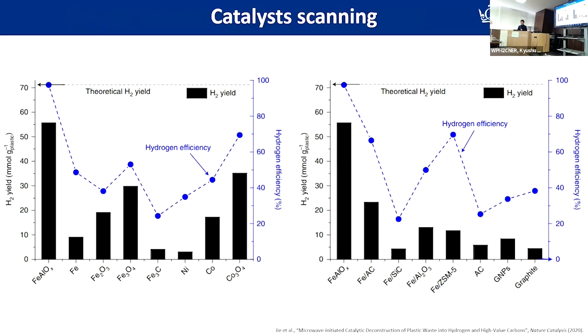So in our work, we scanned very different and a wide range of catalysts. And finally, we found the iron aluminum oxide. This was prepared by an organic combustion method, in which we are not using a supporting material, and we can't tell exactly how small the iron or iron oxide particles formed on site are, but it's just formed through a sol-gel and then combusted. In this form, we find that they have superb microwave activity, and they also retain the good catalytic properties of iron to cleave the carbon-hydrogen bond in the polymers. And they give us a very, very high selectivity to hydrogen, and they retain the carbon on site and produce carbon nanotubes.